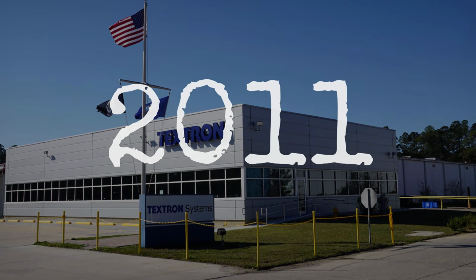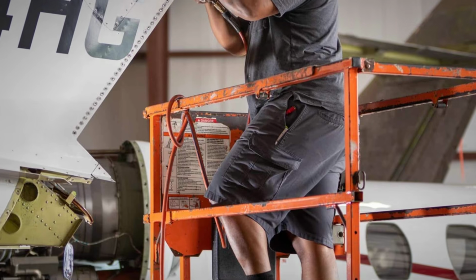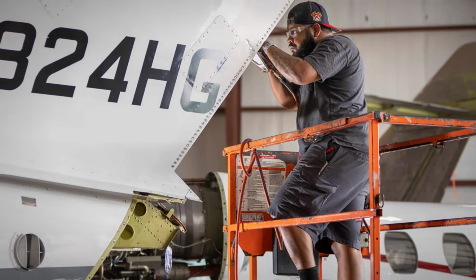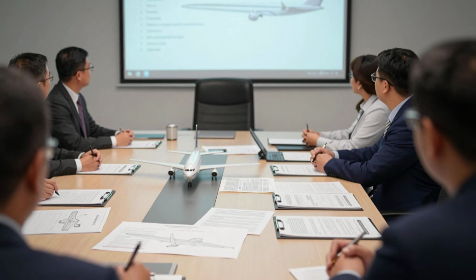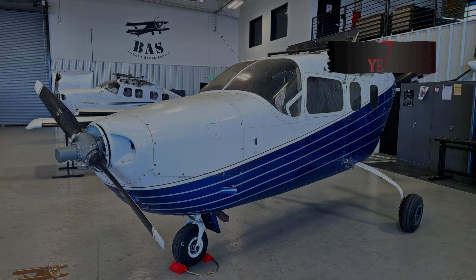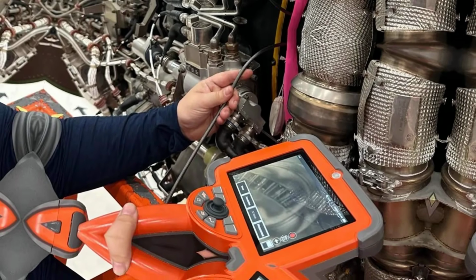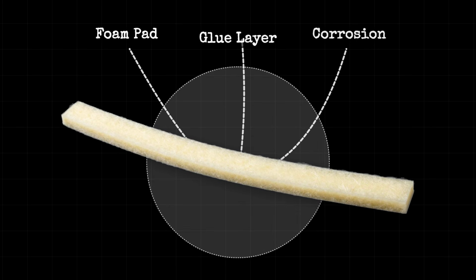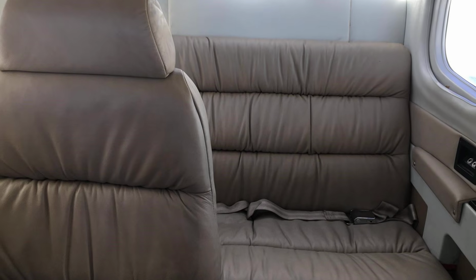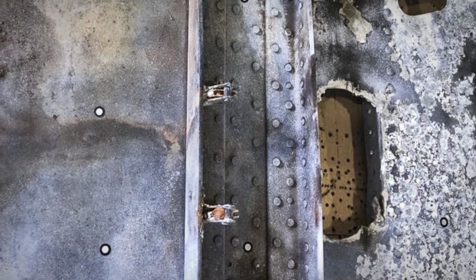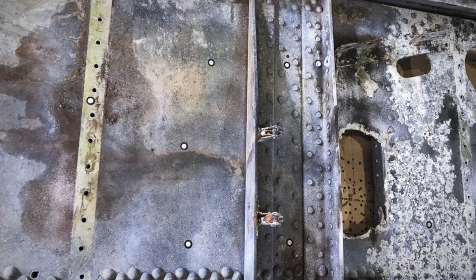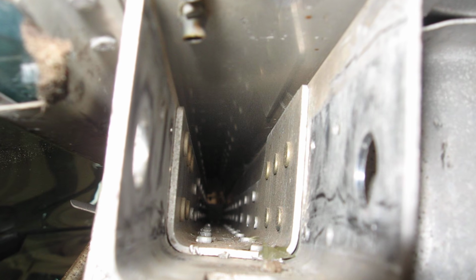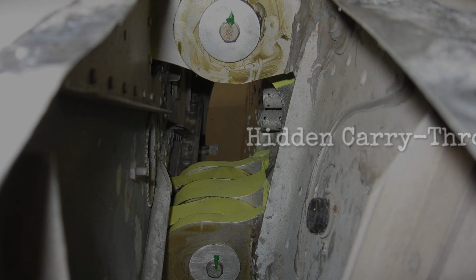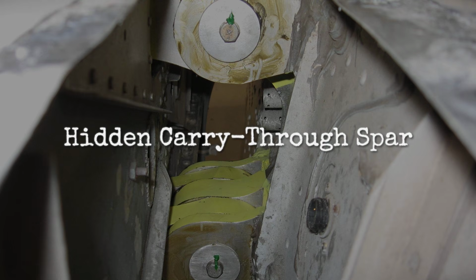In 2011, Textron replaced the eddy current schedule with a visual inspection required every 3 years. The stated rationale was that no spar cracking had been identified in the 19 years the prior program was in place. The design feature that had been hiding the corrosion was cosmetic foam padding glued to the lower spar surface with a highly hygroscopic adhesive. The padding was there for cabin finishing. The moisture-attracting glue beneath it had been slowly drawing water onto the most structurally critical component in the aircraft. Because the padding covered it, nobody had been looking.